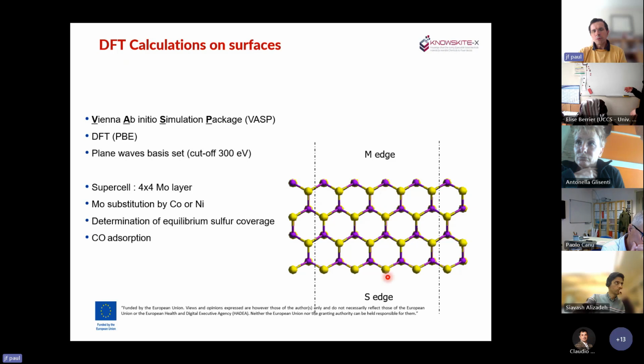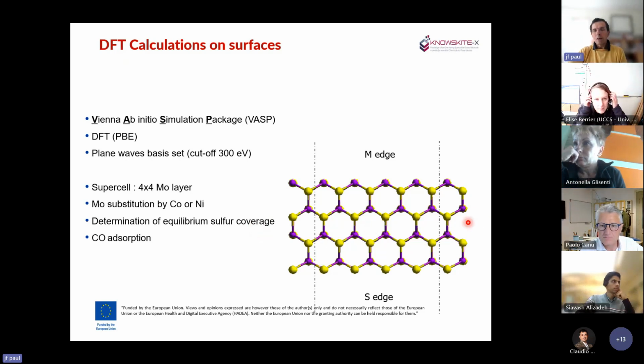And so the two surfaces are far enough from each other to have something which should be a bulk between them. If we had cut it there, for example, in the middle, all the atoms will be on the surface, and so we will not have any bulk inside. Also, it means that we will get results, but they will not be relevant to the models that we want, or to the experimental data on which we want to compare them. So it's important to be sure that the size of your system is correct depending on the type of property you want to consider.